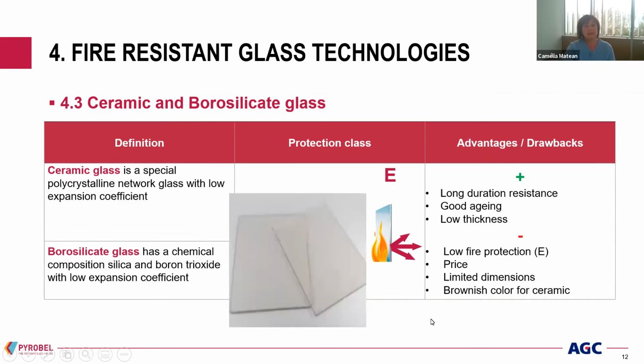A third category is ceramic and borosilicate glass. These are both resistant to fire thanks to their low expansion coefficient when heated. This is for ceramic glass thanks to its special polycrystalline network. Normal glass has an amorphous composition. And for the borosilicate it is thanks to the special chemical composition. It contains some boron trioxide in the composition.